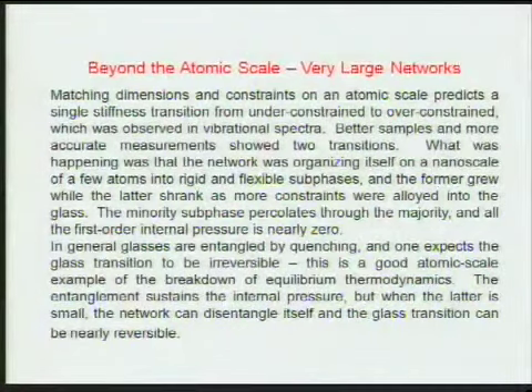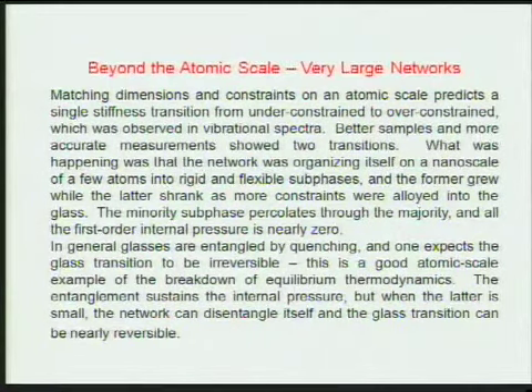Anyway, so now we go beyond the atomic scale to very large networks. These networks organize themselves so that there will be as little stress as possible. And actually, the thing that's pretty is that it had been known for a long, long time that there are all kinds of phase transitions, for instance, the liquid-gas transition, among equilibrium systems. But what we found was that these glasses also have phase transitions, and they separate, however, into two kinds of subphases on a nanoscale, that is to say, on a scale of 10 angstroms or so. And these phases are classified as either rigid or flexible.